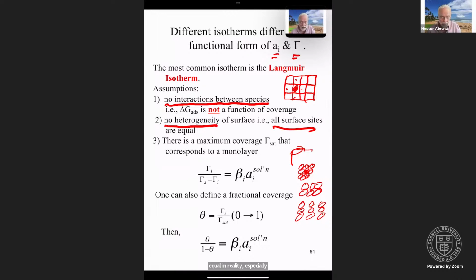And then we also assume that there is a maximum coverage that typically corresponds to a monolayer, and that's a saturation coverage. And from that, then we can write that gamma i, meaning surface coverage at some solution concentration i, is given by the saturation coverage times the parameter that takes into account the free energy of adsorption, and activity in solution or concentration.